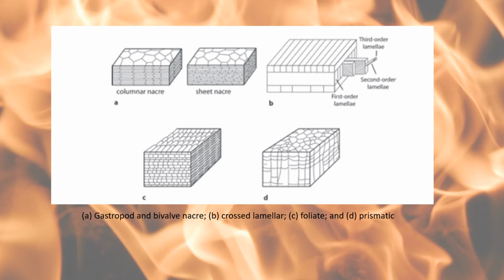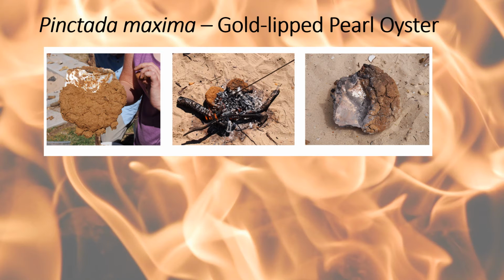One of the first experiments, and one that was a catalyst really for formalising the studies, was trying to replicate a shell working procedure recounted by an anthropologist working in the highlands of New Guinea, and these were to make pearl shell crescents known as kina. And what they would do in order to break up the valve into the bit that they wanted, was they really had to get rid of the hinge, which is the bit I've got exposed there. It's often very thick, but the plane of fracture runs parallel to the shell, so it's not like you can flake it. It's very difficult to control fracture. It's very, very organic heavy. It tends to splinter, it tends to crack back into the shell.